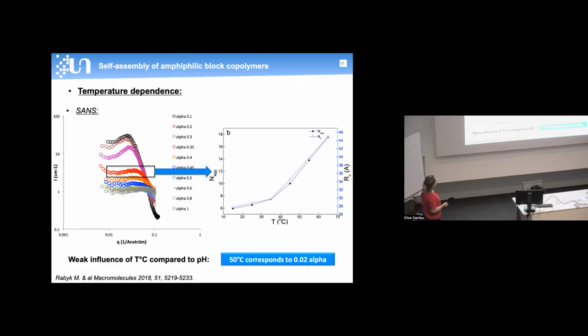And with the model applied, we could also plot the aggregation number and core radius versus the temperature to see that there is an increase with increasing temperature. However, we could see that the influence of the temperature is weak compared to the pH, as it needs a very high variation of temperature to get a small effect in ionization degree.